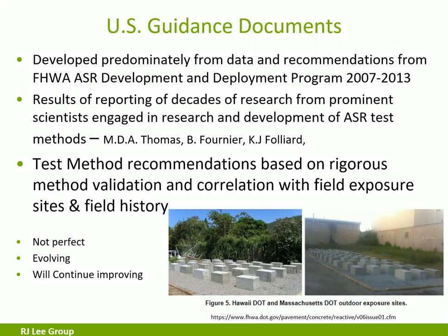The test methods recommended in these guidance documents are based on rigorous method validation and correlation with field exposure sites and field history. They have put exposure sites all over the world in many different environments and different mixes, correlating the test methods to establish long-term performance, and also evaluating the long-term performance of current mitigation strategies. So the information they're getting from those projects gives us the data we need to adjust recommendations and testing based on knowledge and data.